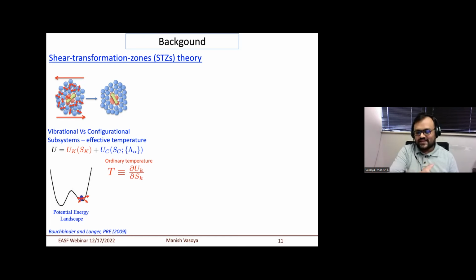But now you have STZs, which are also disordered, because the system is disordered. The STZ is happening very randomly, so thermodynamically or statistically it also has energy, which is the configurational energy. When your STZs or microstructure evolve and induce some deformation, it is through the evolution of the configurational energy. When you take the derivative of that configurational energy with respect to the entropy, you get what is called the effective temperature, which represents your configurational or internal microstructure. And S_c is the configurational entropy.